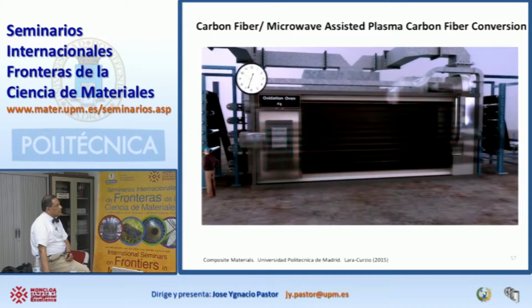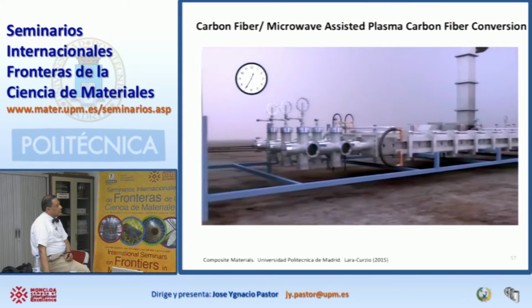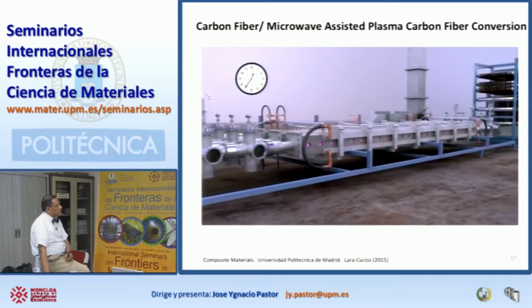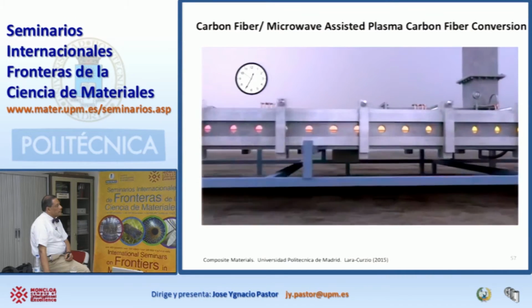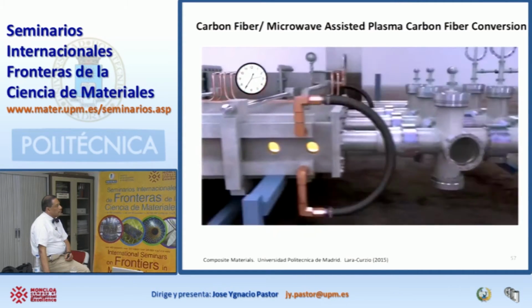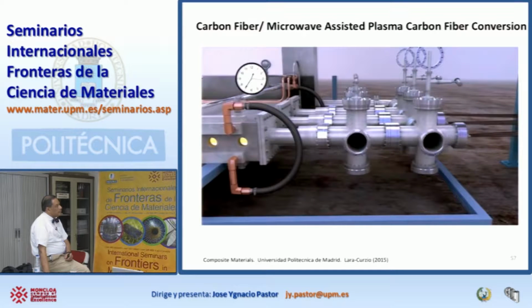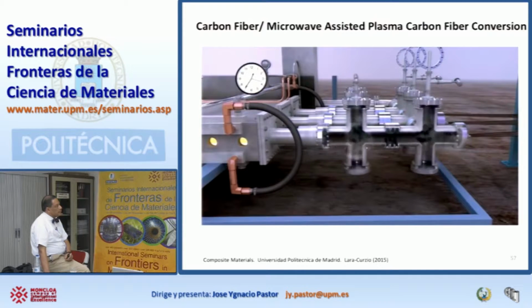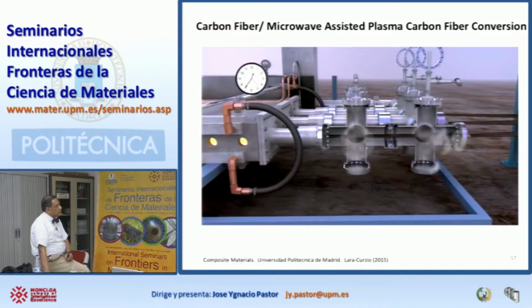The fiber then enters the carbonization phase. Microwaves and plasma provide the energy needed for carbonization. Approximately half the material is vaporized, with gases exhausted through an incineration system that is much smaller, less expensive, and requires less energy than conventional processing systems. The remaining material is nearly 100% pure carbon as it enters a surface treatment process that renders it chemically compatible with resin.